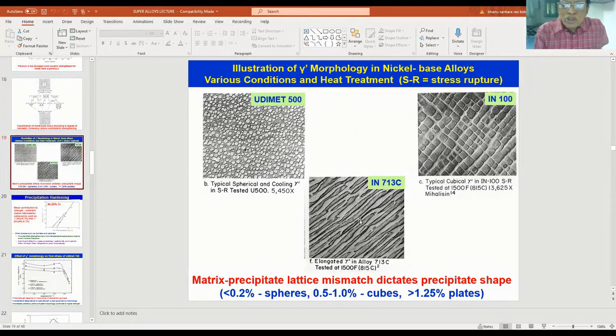In the previous slide, I talked to you about the lattice mismatch between matrix and precipitate. That lattice mismatch dictates the precipitate shape. If the lattice mismatch is less than 0.2%, gamma prime precipitates in the form of spheres. If the mismatch is between 0.5 to 1%, it forms in the form of cubes. If mismatch is more than 1.25%, it forms in the form of plates.